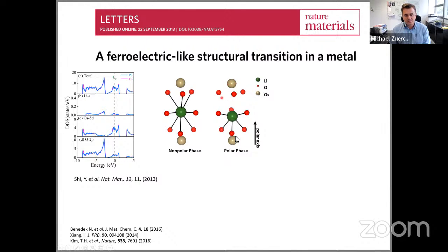And at the same time, it was confirmed that this is indeed ferroelectric in its low temperature state. At the same time, one looked at the density of states of those systems, confirming that indeed it's metallic. There is a non-zero electron density around the Fermi level, and it was confirmed that this electron density basically stems from the osmium atoms. So in a way, one can think of the system as osmium contributing the metallic behavior, and the displacement of lithium contributing the ferroelectric portion of the system. And the special configuration of the unit cell allows the dipoles to interact with each other and create long-range order.